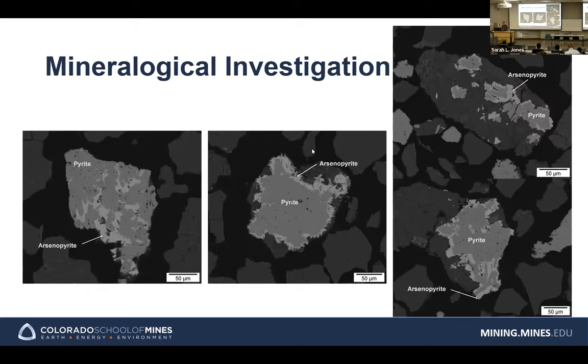And why does that happen? These are actually some backscattered SEM images. As you can see, we have a lot of pyrite. The darker area is pyrite, and the slightly lighter area is arsenopyrite, so it has arsenic in there. And then, as you can see, the arsenopyrite is sort of inside of the pyrite matrix.